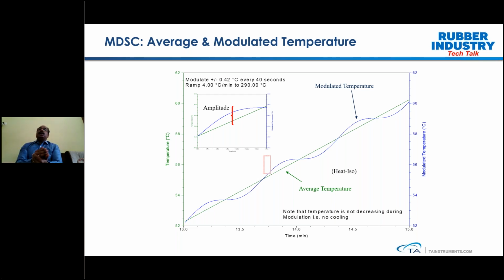In MDSC, again just like modulated TGA, instead of applying a linear ramp, we apply an oscillatory temperature ramp at a fixed amplitude and period. In this particular case, if you take a small portion of the heating ramp, you can see a sinusoidal temperature ramp with a variation of plus or minus 0.42 degrees centigrade and a period of 40 seconds. And the overall ramp we are maintaining at 4 degrees per minute up to a temperature of 290 degrees centigrade.